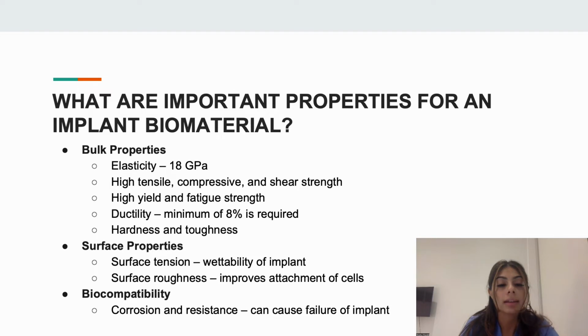When looking at tensile, compressive, and shear strength, you want them to be high to prevent fractures and lower the stresses on the implant. When looking at yield and fatigue, they need to be high. They also need to be high to prevent brittle fracture under cyclic loading. For ductility, according to the ADA, a minimum of 8% is required for dental implants. This is important for contouring and shaping of the implant to fit in the jaw.